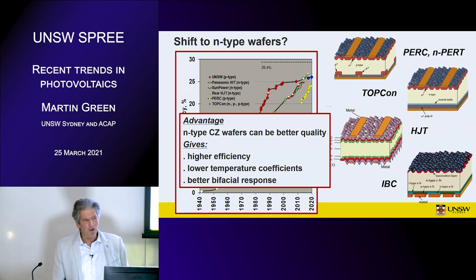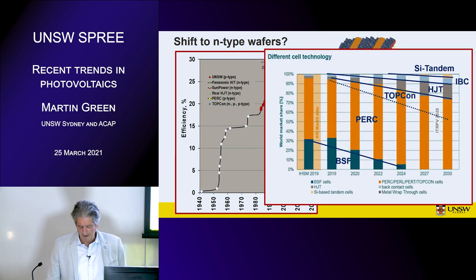So where you've got these small target areas for the carriers to get to on the back, you need diffusion lengths that are even greater than 10 times the wafer thickness. So you need really good quality material for a different reason. These two structures aren't as robust. They're really dependent upon good quality material. But if you have the good quality material, they can give those advantages.